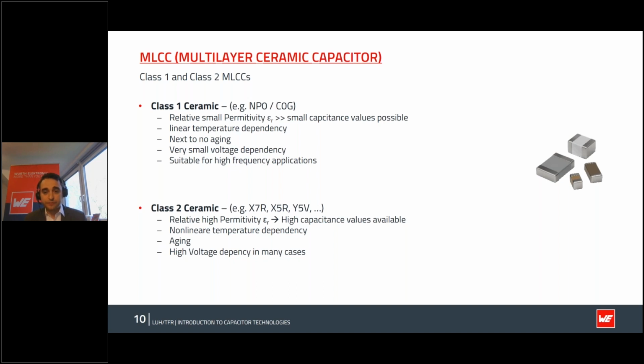The class two ceramics on the other side, you mainly hear X7R, X5R, or Y5V. This is all according to the US standards, as the European ones are not used anywhere. The X7R defines as the X is the negative temperature range for minus 55 degrees, the 7 for 125 positive range, and the R defines the capacitance change to plus minus 15% over temperature. The X5R similar is just the positive temperature range is plus 85 degrees, and the Y5V is minus 30 degrees up to plus 85 degrees. And the capacitance can change plus 22% and minus 82%, so quite significantly.